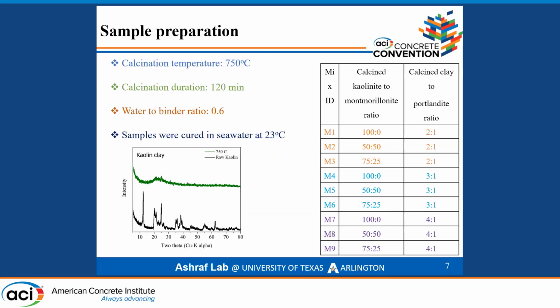XRD pattern, the black one is the raw kaolin and the green one is the calcined kaolin at 750 degrees Celsius. Kaolin clay actually becomes totally amorphous at 750 degrees Celsius. That is why we chose this temperature. The calcination duration was 120 minutes. The water to binder ratio was 0.6 and the samples were cured in the seawater at room temperature.